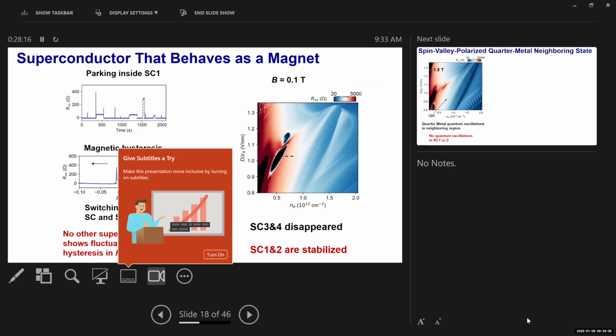But do you have samples that just show zero resistance as a function of magnetic field, no switching? It does. As you can see here, the coercive field of this particular case is very tiny, like 20 millitesla. We do have samples that show bigger coercive fields, like several times bigger, and in those cases, the fluctuation happens much less frequently. But with the switching, do you still see finite resistance? There is, if you are patient enough, there could be a switching, but it's much less frequent than here.